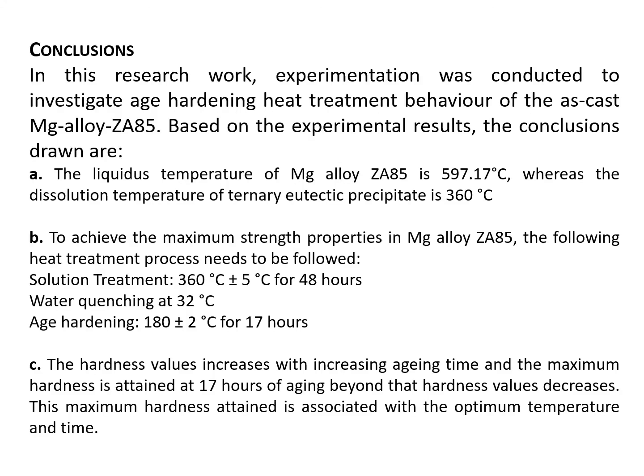Conclusion. In this research work, experimentation was conducted to investigate the age hardening heat treatment behavior of the as-cast Mg alloy ZA85. So the following conclusions are drawn. A. The liquidus temperature of Mg alloy ZA85 is 597.17 degrees centigrade, whereas the dissolution temperature of ternary eutectic precipitate is 360 degrees centigrade. B.